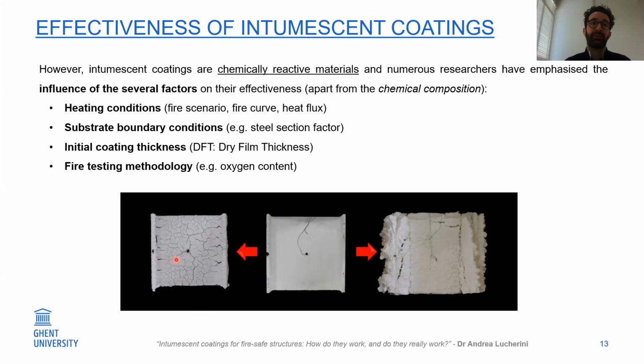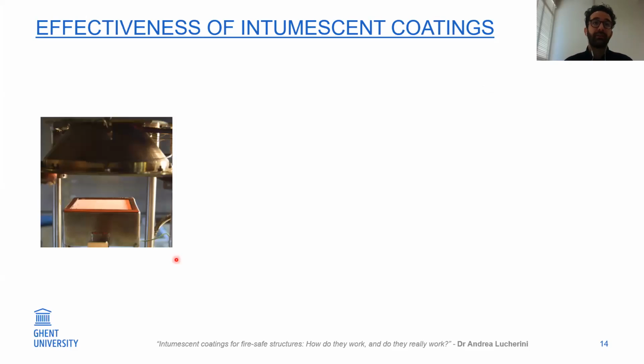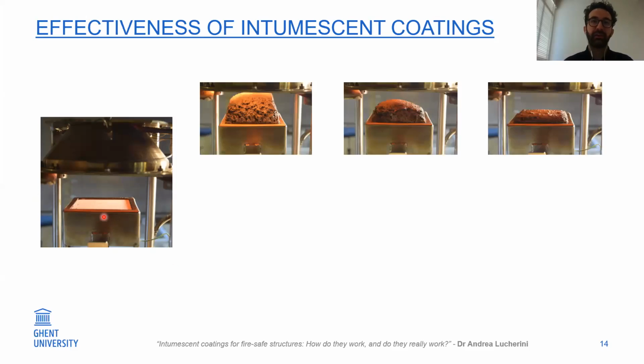This is very important. And this is another example that I showed you earlier, using a testing apparatus called a cone calorimeter, that you can see here. I have a steel plate coated with intumescent coating, and you can see that at the end of applying different conditions, I got different swelled coating at the end of the thermal exposure.